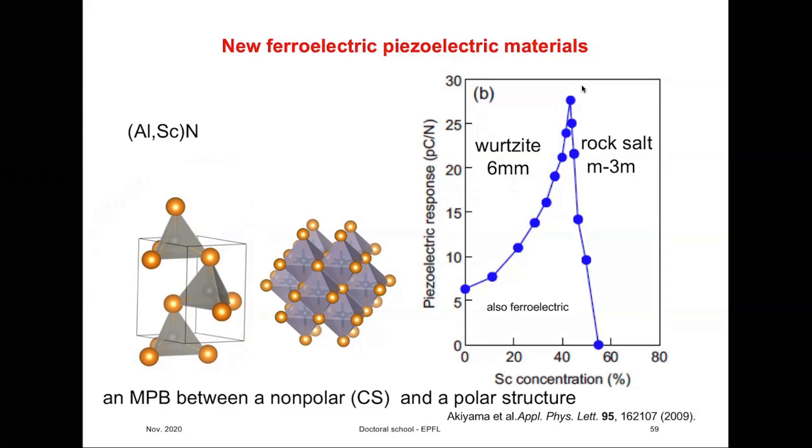It's polar, but not ferroelectric, so you cannot polarize it. You cannot make piezoelectric ceramics with randomly oriented grains, but you can do that with thin films, and just like zinc oxide, which has the same structure, it would grow in a column-like structure in which the majority of the grains are oriented in the same direction, and you get some polarization.